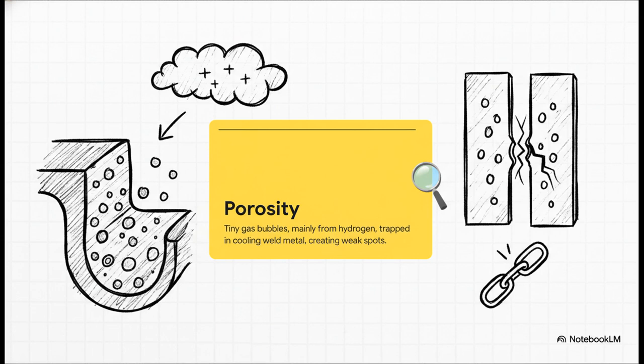Okay, so let's zoom in on that first big headache, porosity. Just imagine these tiny little pockets of air or gas trapped inside the solid metal. These bubbles, which are usually hydrogen from any tiny bit of moisture, dissolve right into the molten aluminum. But because the weld cools down so fast, that gas can't escape in time, and you're left with these little voids that can seriously weaken the whole joint.